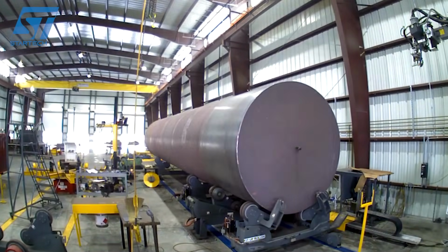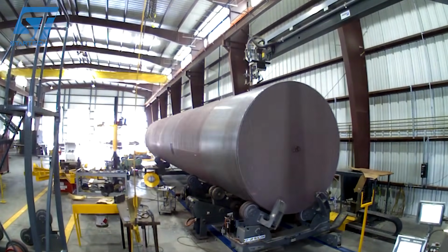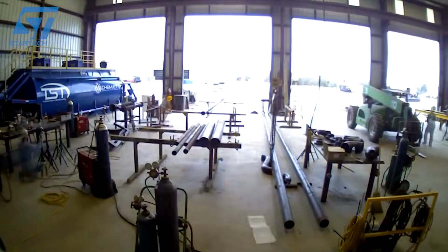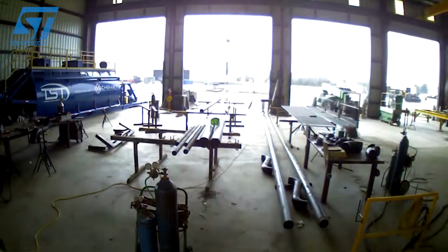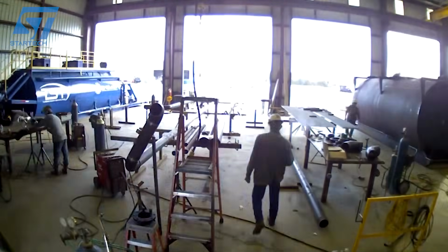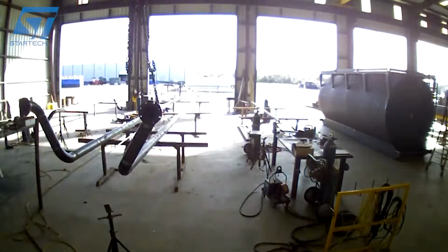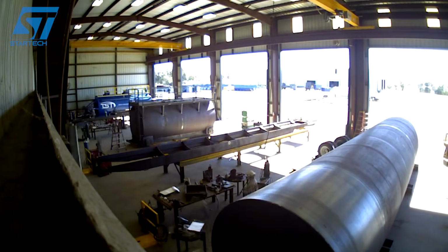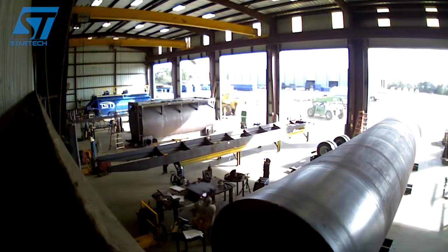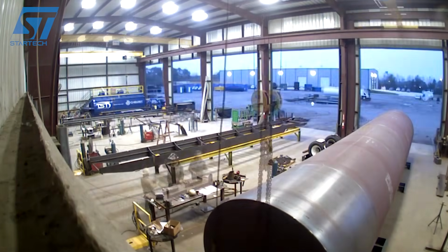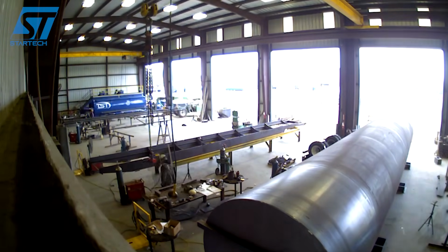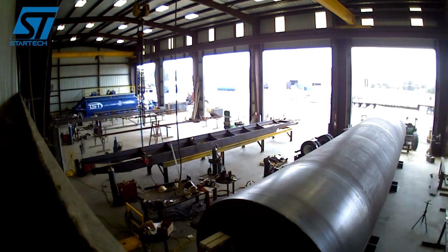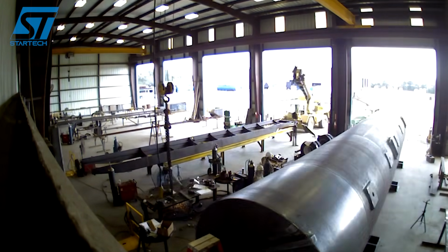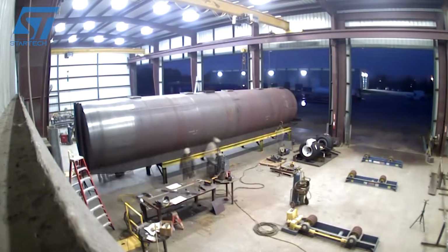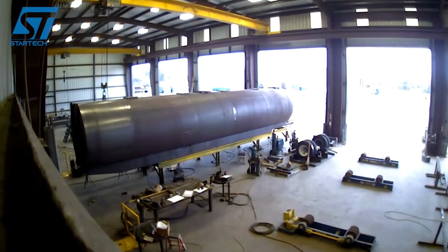After welding, every seam is inspected. Radiographic testing, X-ray or gamma ray, reveals internal defects invisible to the eye. Ultrasonic testing maps wall thickness and detects planar defects. For smaller fittings, magnetic particle or liquid penetrant testing checks surface integrity. Finally, the completed vessel is hydrotested, filled with water and pressurized to 1.3 times the design pressure, and every weld is checked for leaks. Only after passing all these steps does the tank earn its nameplate and leave the shop.